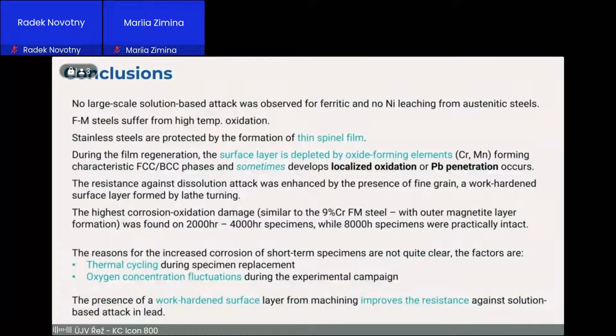So to conclude this, we have no large-scale nickel leaching. That's the key message. The second important thing is that the surface fine-grained, work-hardened layer created a nice corrosion resistance against the dissolution. Oxide layers are damaged by thermal cycling during specimen replacement because they crack and then develop some localized attack. And 9% chromium steels are suffering from high temperature oxidation at a higher rate than stainless steel. Okay.